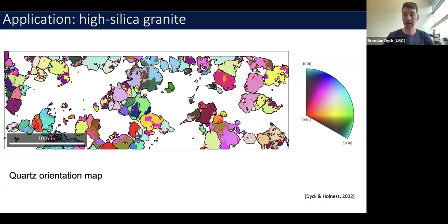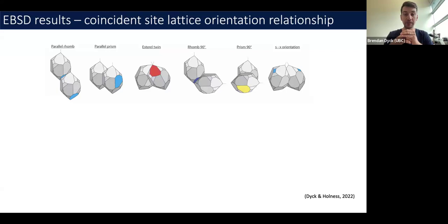And if we do an EBSD map, this is just a color-coded orientation map. Now, our eyes don't pick up on any really useful patterns in a map like this, but we can query this data for certain grain boundaries that have these low energy orientation relationships. And when we do that, we can take this kind of idealized view of the different ways in which these quartz crystals can come together. They can meet on rhomb planes, prism planes. They can also meet on the s or x planes, some of the smaller planes, less frequent for them to meet on. But then they can either meet in parallel orientations with regard to their c-axes. The Dauphine twin is, I believe, about 60 degrees apart. Or we could look at orientations, for example, meeting on the rhomb planes, but at 90 degrees, or the prism at 90.